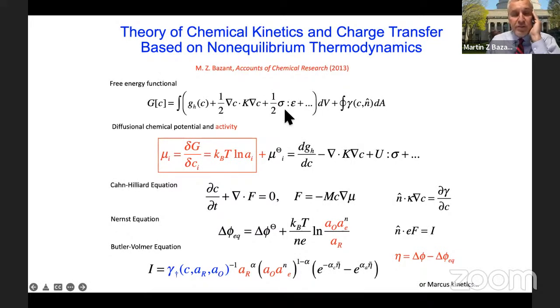Also, in solid materials, such as these battery materials, it's very important to take into account chemo mechanics. As lithium inserts itself into the crystal, there's a misfit strain. So the lattice changes its shape and size. And so whenever there are gradients in concentration in the system, you have, for example, an expanded part of the crystal and a contracted part of the crystal, and that leads to mechanical energy, where sigma here is the stress tensor and epsilon is the strain tensor.